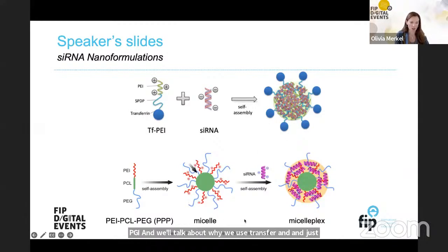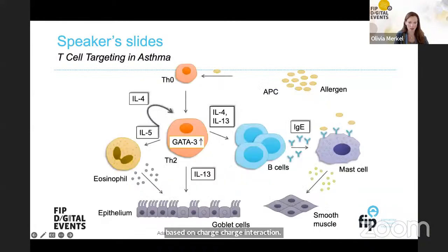And then in the lower part, you see a polymer that we often abbreviate as PPP because it's a PEI coupled with polycaprolactone and polyethylene glycol. And this amphiphilic material then forms micelles and self-assembles with siRNA, whereas the transferrin-modified PEI simply interacts with siRNA based on charge-charge interaction. So the reason why we made transferrin PEI, and that idea obviously was not entirely new,